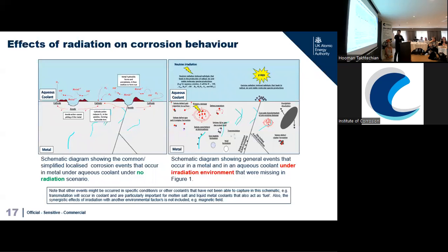So this is just two schematics showing the radiation impact on corrosion behavior. Left-hand side here is a schematic diagram showing the common, simplified local corrosion events that occur in metal under aqueous coolant. And right-hand side here is when radiation comes into play. The radiation itself will interact with water, forming radicals and ions, and basically cause the species required to accelerate corrosion. At the same time, the highly energetic radiation will also interact with the materials themselves. Materials that are not susceptible to corrosion will become susceptible, in the sense that radiation enhances diffusion of certain chemical elements and forces them to precipitate out from the alloy or from the matrix itself. It causes depletion of certain elements that actually give strength or corrosion properties to materials and changes them locally. Because of that, you have more localized corrosion.